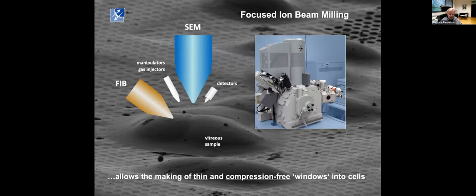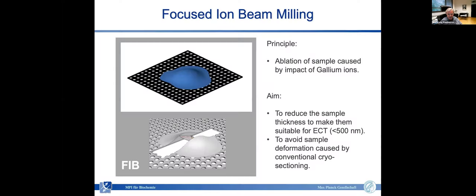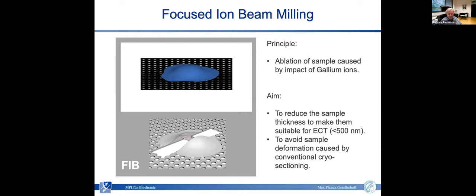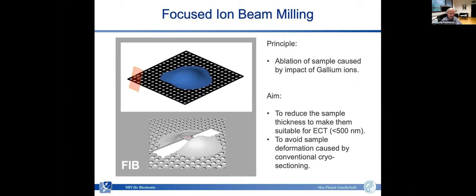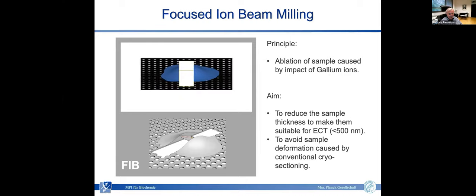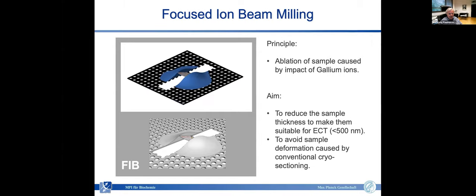So we put our money into developing focused ion beam milling. Basically we use a dual beam instrument, the SEM, which is used to monitor and to target the right region. But then we have a focused beam, a gallium beam, for ablating material and for local thinning. And that allows us to make thin compression-free windows into the cell. Many different geometries one can use. One can cut basically a wedge. That is what people often do with, let's say, bacterial cells or something thinner. But what we do most of the time, and that has again become common practice, is we ablate material from above and below the region of interest. So we have a thin lamella that is supported only by the surrounding ice.